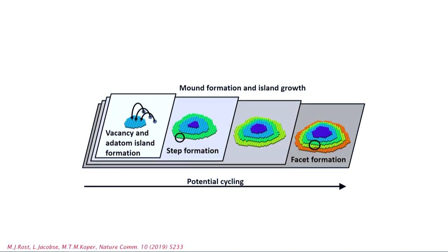So we have this mound formation, and the atoms forming these islands, they come basically from the vacancy. So we make these stripes of platinum oxide. We basically have to remove one platinum atom. It presumably then still hangs around on the surface. Then we reduce. That platinum atom will not go back into the original vacancy because of a barrier that is associated with hopping back into the vacancy. And so this is really at the heart of the roughening.